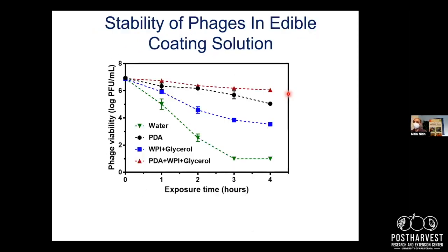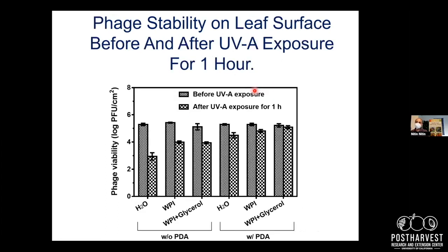Again, this is the case if you were to spray it on a product and it was exposed to light, you would lose significant activity without this protective coating, as illustrated here. And one of the next tasks for us was to see if it would work on a produce surface, and we can expose the produce to that environment and test it. On a produce surface, the loss is even more acute. So for example, you could lose about 3 to 4 log if you just spray this agent on a produce surface. And that's a big barrier in using some of these biocontrol strategies for foliar applications. When you try to spray on a plant and you cannot protect the biocontrol agent from desiccation loss or UV induced damage, some of these coatings could provide those barriers.